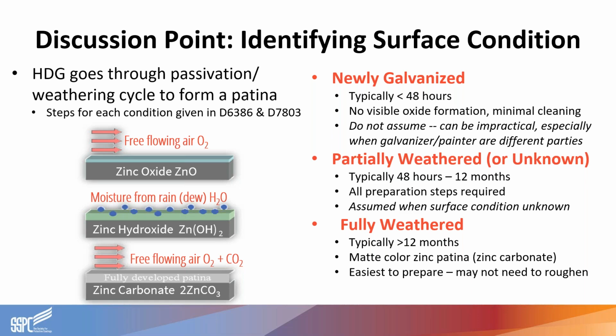Only in cases where the galvanized steel has been left to weather over a year or has fully formed the zinc patina, meaning that there's only zinc carbonate on the surface and none of those problematic oxides or hydroxides, do the standards recognize this condition as a little bit easier to paint with fewer preparation steps required. But for the purpose of this presentation, I'm going to focus on the partially weathered galvanizing and some of the communication issues that can arise with the surface preps required for that case, since it requires the most preparation steps defined in the standards.